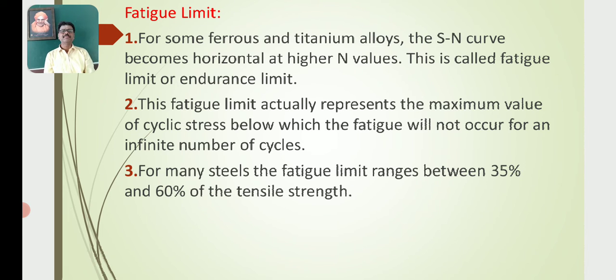Then what is the fatigue limit? The fatigue limit represents the maximum value of cyclic stress, or cyclic load, or cyclic external force per unit area, below which fatigue will not occur for an infinite number of cycles. For many steels, the fatigue limit ranges between 35% to 60% of the tensile strength. So this is the comparison between the fatigue limit and the tensile strength of the same material, with steel as one example. The fatigue limit range is different for different materials.